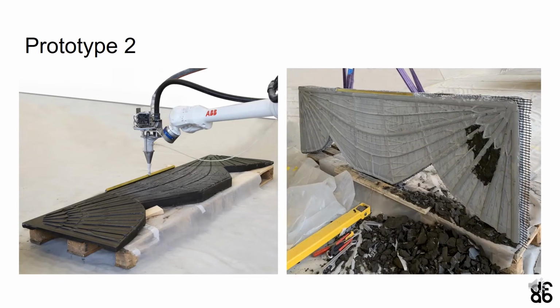For this prototype, the print path was adjusted to follow the patterned ribs of the formwork. As you can see in the right image, not all of the release agents performed well. We decided for the middle one, which was a commercially available water-based release agent.